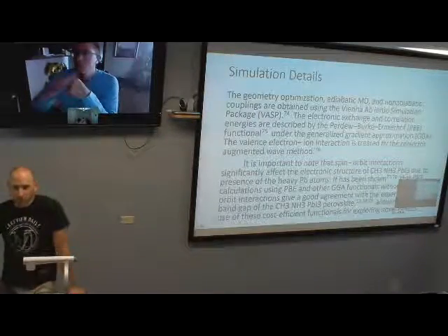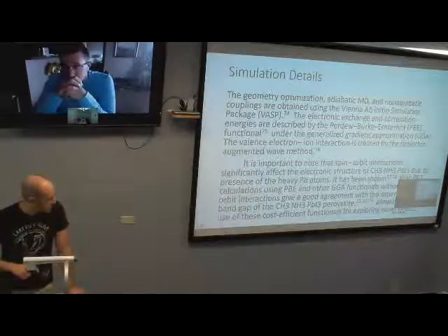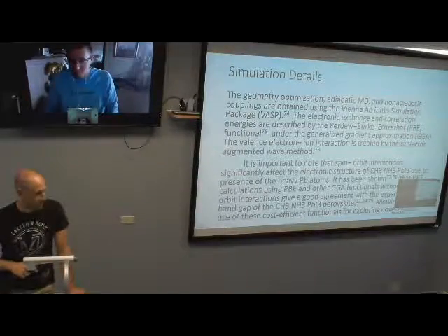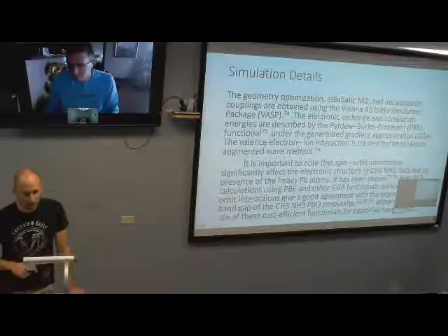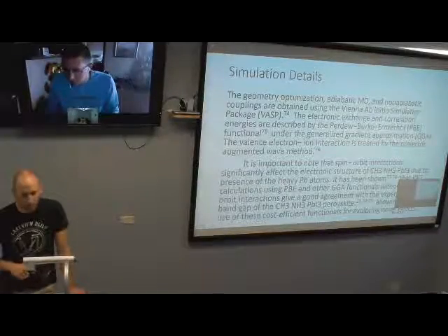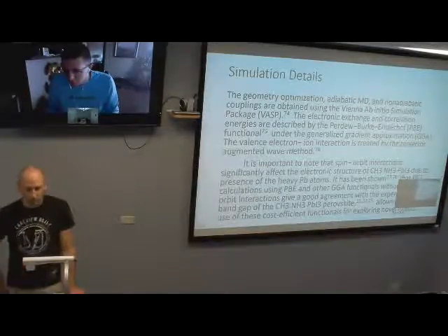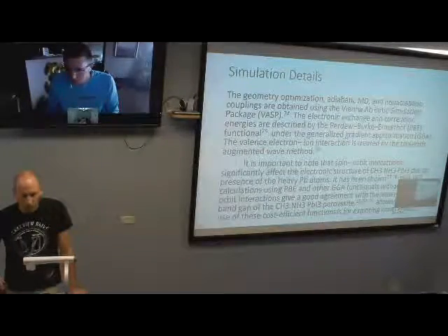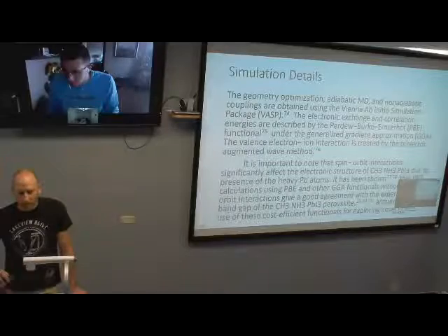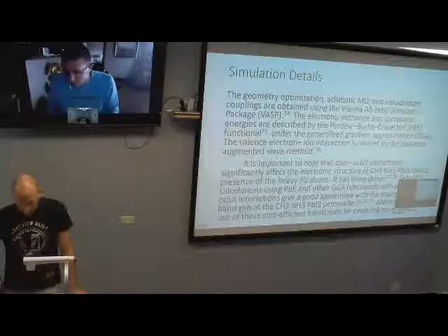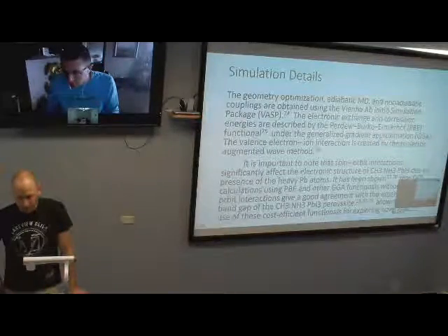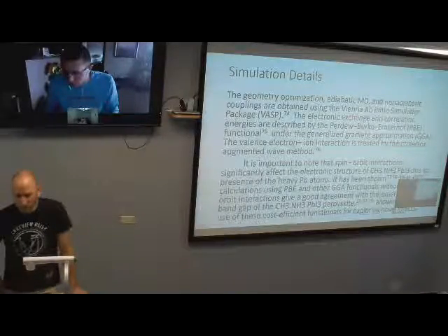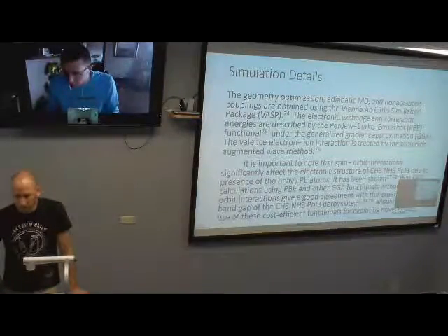As far as I know, these at least get you pretty close with perovskites. With semiconductors, they definitely don't. So it's known that you just use regular GGA functionals and the optical gaps are very close to what is seen in experiments. With perovskites, I believe that is pretty true. Close. So you really don't need to go to hybrid functionals or anything more advanced with perovskites?